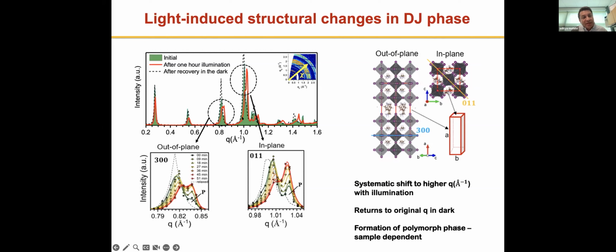That's what we start with. We light soak it for some amount of time, and we get this contraction in the real space of the lattice. And then if you take the light off, it relaxes back and goes back to its original position. And so we wanted to understand what was really going on in both the in-plane and the out-of-plane directions.